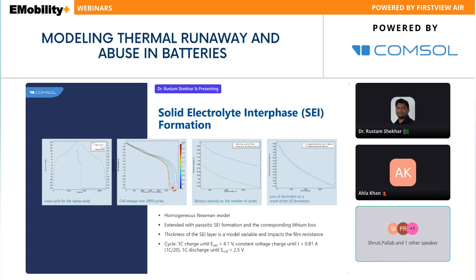with the different discharge curves. So as we can see, the first discharge curve lasts more than 3000 seconds, and when we go for a higher number of cycles, it drops below 3000. That means while running the battery, we are increasing the SEI formation, where we are losing capacity, and that is affecting the performance. That is increasing the IR losses, and then that is going nearer to the failure scenarios. So this is one comparison of discharge curves, and similarly we can compare with the cycle number.